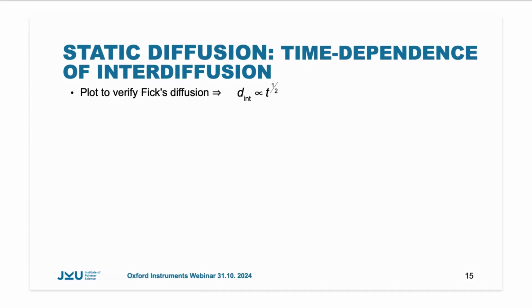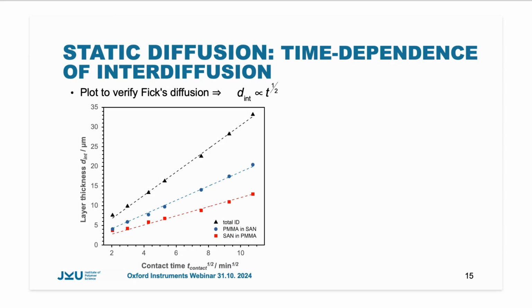Now we have to verify that we really have diffusion, and when we talk about diffusion, normally we talk about Fickian diffusion, meaning that the thickness of the interfacial layer is proportional to the square root of the time. Thus, plotting the results from the slide before versus the square root of the time, what we see is that we have nice lines.